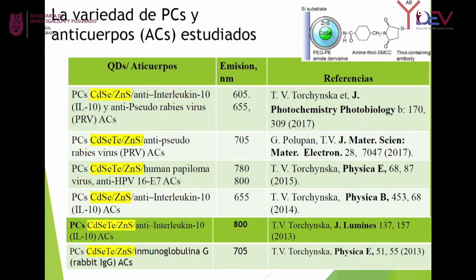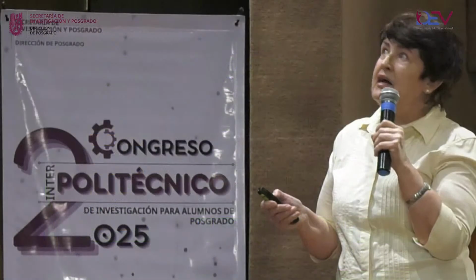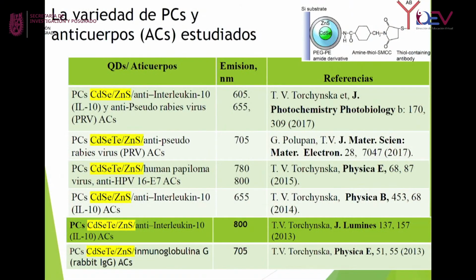With the change of size and also with the change of composition of the material, we obtain different light. Here you could see wavelengths in nanometers. Red is 605, 655, then near infrared, then 800 infrared. This is our publication where we published our results.